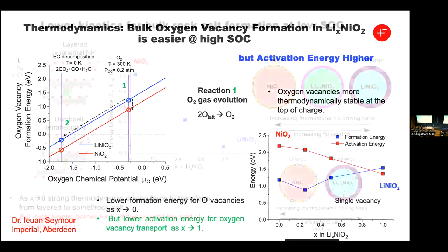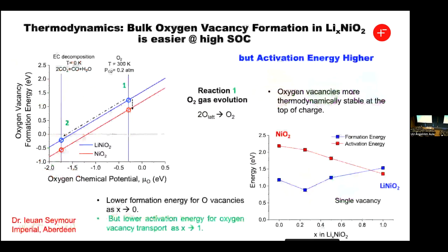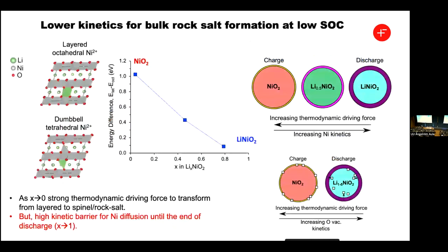Then the other thing to think about is what about the activation barrier for it? And what's interesting is if you're at high states of charge, if you're at NiO2, then the activation barrier to move the vacancies, which is what you need if you want to go from pulling vacancies out from the surface to form a rock salt structure, is very high. But if you go down to lithium nickel oxide, the reduced state, the vacancy migration energy drops. And the same thing actually happens for the nickel migration.